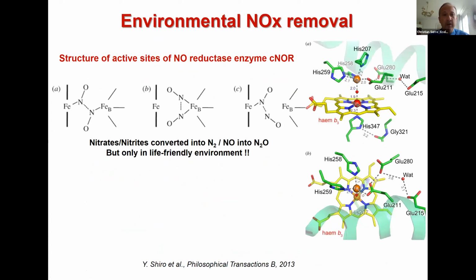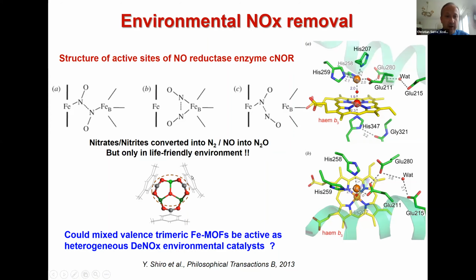If you look now at enzymes, some of them, like NO reductase, are capable of nitrite or NO transformation under life-friendly conditions. The structure of the active site is a dimer of iron with a heme and a non-heme complex. They are close to each other, and you can see here the mechanism that has been proposed for the transformation of NO, which includes bond breaking and reforming. As you see here, this is a trimer for an iron MOF, and you can imagine the similarity with two consecutive iron 2, iron 3 sites. So the question at that time was: could these mixed valence MOFs also be efficient, but this time not in liquid phase, but under air at room temperature with water?